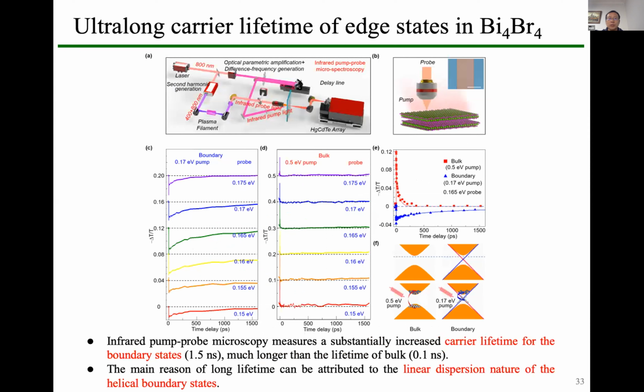Then we use this setup to study their lifetime. We use an infrared pump-probe technique to study their carrier dynamics. It is clear that the negative signals are around the boundary, but at the bulk there is a positive signal. The difference is that for the boundaries, the lifetime is very long, about 1.5 nanoseconds. But for the signal from the bulk, the lifetime is very short, about a few tens of picoseconds. So this is very different dynamics.